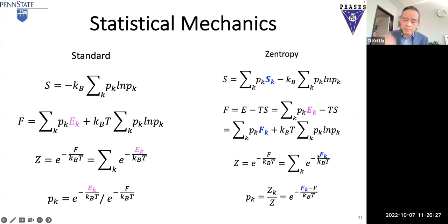And we didn't know that before, but now we look in the literature, and there are actually quite a few papers showing this equation, but nobody used it. We are probably the first to really use this equation to solve problems. But that's very significant because what most people do is calculate F_k, right? Then they do this hybrid model, as I mentioned before. They do F_k, they develop a Hamiltonian for the system based on the F_k. Then you do the MD or MC simulation. In that case, you have another modeling procedure. Your data is not as accurate as the DFT itself before. So then you lose a lot of the features.